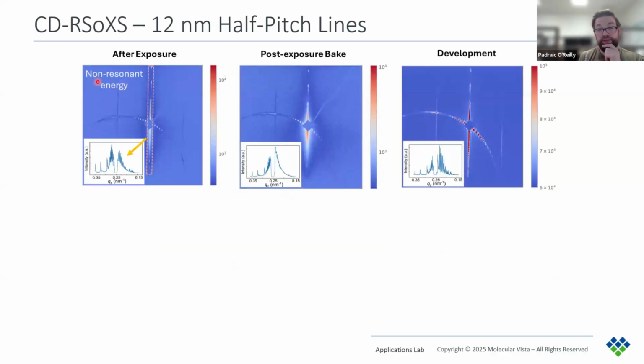So here we have the non-resonant energy plots for all three samples. Now in these plots, this energy is mostly sensitive to the topographical structure. So I want you to focus on the insets here, where this gold arrow is pointing. And these display the 1D plots of the scattering intensity along the long edge, where this gold dashed box is. And essentially, if you see these sort of scattering lines here, there are periodic topographical structures.